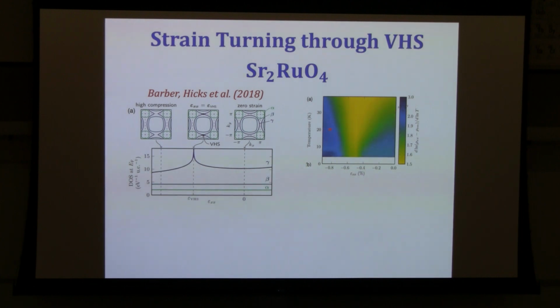What you should see here roughly is that it's bluish on this side, bluish on that side. That corresponds to an exponent of 2. This is what you would expect in a Fermi liquid. But close to this special value of strain, you see this fan-shaped region where the exponent seems to deviate significantly from 2. It's below 2. This is a behavior that you would usually associate with some kind of quantum critical point. You would imagine that at zero temperature, there's some critical point that you can't quite reach, but you can try to approach from higher temperatures. And the behavior of this quantum critical point would manifest itself in anomalous scaling that would extend in this fan-shaped region in the strain and temperature plane.